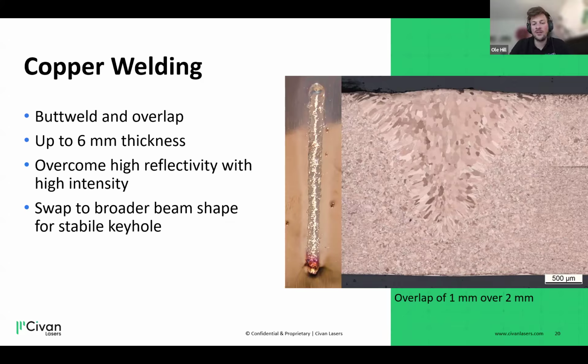I'm sorry, I forgot to mention, this reflectivity issue is really only true for solid copper. Once the copper is in a liquid form, the absorption rate in the infrared increases by a few magnitudes. So it's only really about overcoming the solid, mirror-like copper surface. We use a very concentrated beam shape for the first millimeter to create molten copper and a small keyhole. Then we switch to a bigger beam shape, which creates a more stable keyhole. And that allows us to do different kinds of copper welding setups.